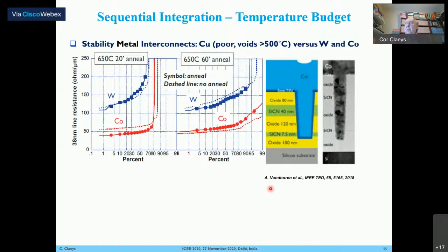But you have to be careful. If you do processing in the top layer, you have to control thermal budget. One example here is, for instance, the copper interconnects. If you go higher than 500 degrees centigrade, the interconnect is becoming very poor and you get voids. That's why people are looking, for instance, at tungsten or cobalt. And here you see, for instance, the performance of tungsten after a 1 hour anneal step at 650 degrees centigrade. Both tungsten and cobalt are performing much better than copper.